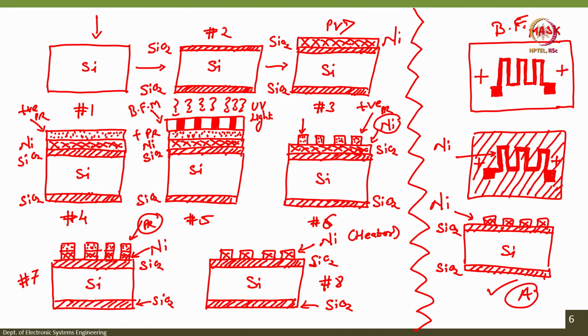When you do that, the unexposed region will be intact, as you can see here, or in another way, because it is positive photoresist, the same pattern that is there on the mask will be replicated on the wafer, which you can see in number 6. After that, you need to dip the wafer into the nickel etchant, because you have to etch the nickel. Before you dip the wafer in nickel etchant, the next step after 6 is hard bake, right. Hard bake is done at 120 degrees centigrade, 1 minute on a hot plate, followed by nickel etchant.